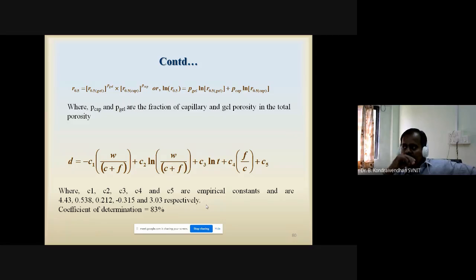Then in a similar manner to what I established in case of OPC paste and OPC mortar, we have done the dispersion coefficient model also. So here the dispersion coefficient is a function of water binder ratio and curing age. Okay, so we also established the relationship for the dispersion coefficient. And what is the application? So now we have to look for the application, because once you have modeled the pore distribution parameter, then what is the implication or application?